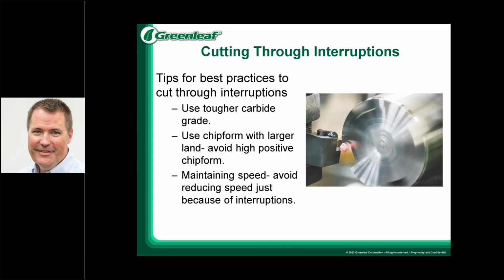Also using a chip form that would have a larger land. The land's going to be that flat surface towards the edge of your insert, with even a heavier hone on that as well to help it hold up through the interrupted cuts, and making sure to maintain speed throughout the cut. A lot of times when you get into those interruptions, they have some extra vibration. The tendency is to try and slow down. However, you do want to try and maintain the same speed throughout the cut as much as possible.